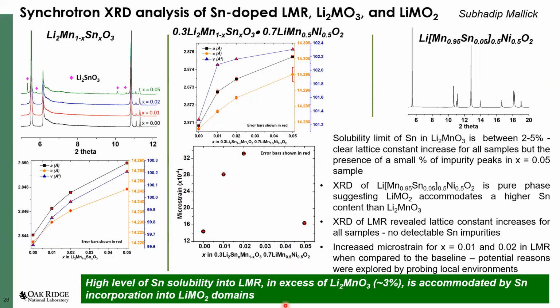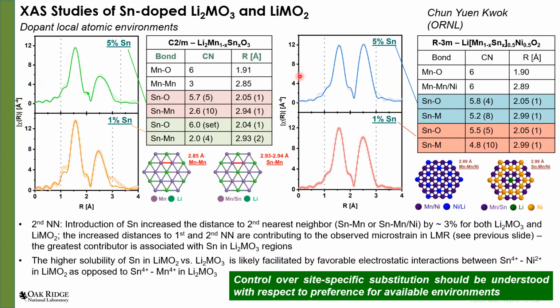So we show relatively high solubility of tin, and most of the tin is present in these lithium and manganese rich regions. So to further understand the tin local environment, we carried out X-ray absorption spectroscopy, from which we are able to clearly show that the tin does go into manganese-like sites. And we also show that the local bond distances that are formed are elongated due to the presence of tin. And we believe that this local increase in bond distances causes coherency stress around regions where the tin is not present. And this is what is creating the strain that is seen in these average experiments that can be done with XRD.